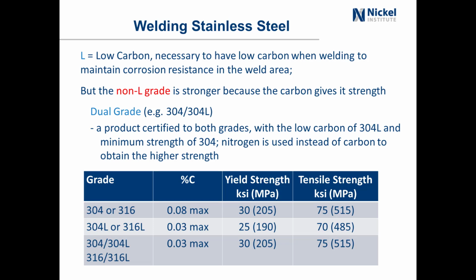And now with regards to welding of stainless steel, and this is with regards to L grade. L means low carbon, and it's necessary to have low carbon when welding to maintain corrosion resistance in the weld area. But there is the non-L grade, which has a higher carbon content, because carbon gives it strength. But there is a dual grade, like 304/304L or 316/316L, and it's a product that's certified to meet both the requirements. It has the low carbon of the L, but it meets the minimum strength of the non-L because a little bit of nitrogen is added in place of the carbon to maintain the strength level.